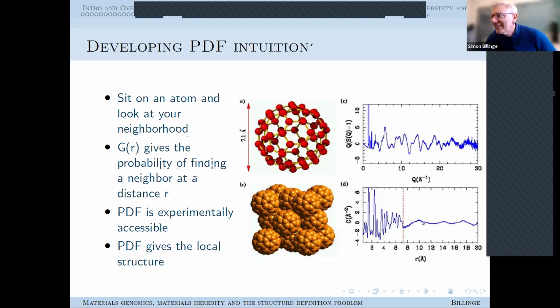You can see there's a little bit of intensity out here, and that's actually coming from the molecular packing. So I can equally well sit on an atom on this ball and look at an atom on this neighboring ball and find the interatomic distance. And what I see is that there's a broad peak peaked at 10, and 10 angstroms is the center-to-center distance of these two balls in this packing. And this is an FCC packing, and so the second neighbor distance is root 2 times 10, which is 14, and the third neighbor distance is root 3 times 10, which is 17. And so these three broad bumps here are telling us about the crystallographic arrangement of the balls in space. So not atom-atom correlations, but these are ball-ball correlations.